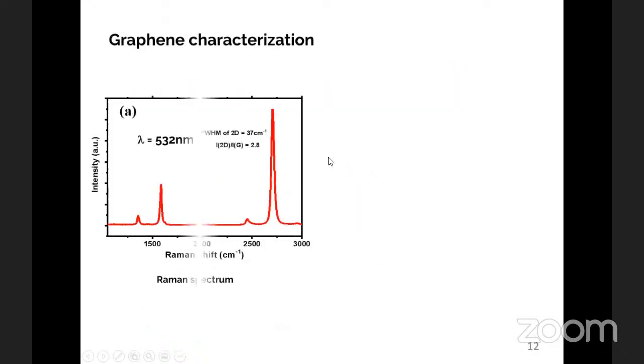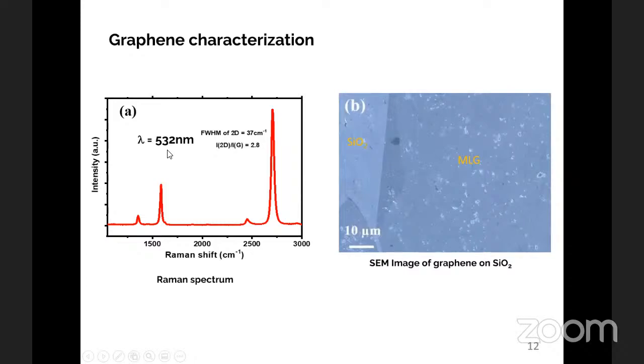After I transferred the graphene, I characterized it using Raman spectroscopy and SEM. Raman spectroscopy reveals the formation of monolayer graphene, and SEM also reveals monolayer graphene, but unfortunately there are a lot of PMMA residues. Later, I completely reduced the residues, but unfortunately I don't have the image to provide you. I'm sorry about that.